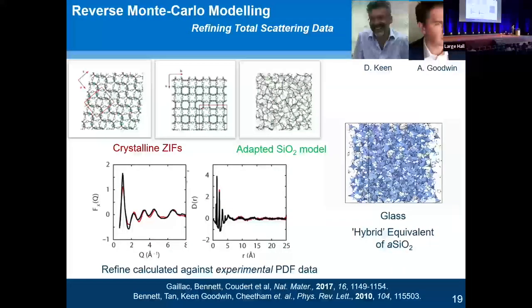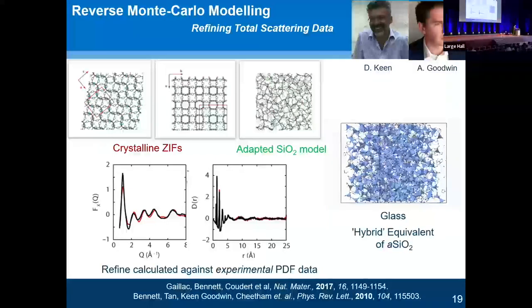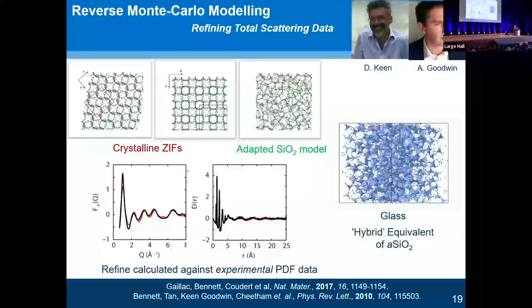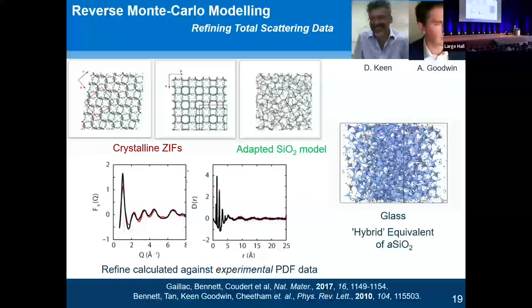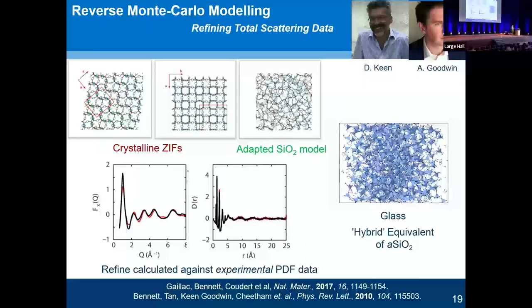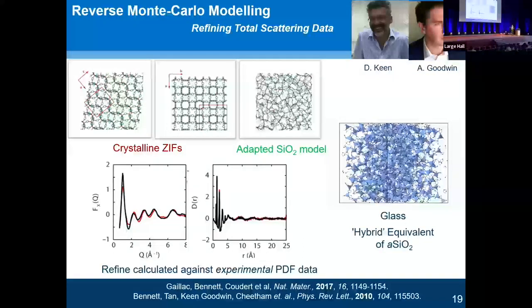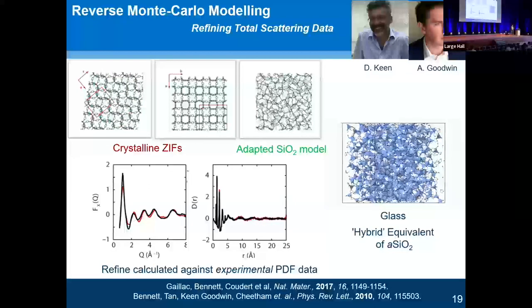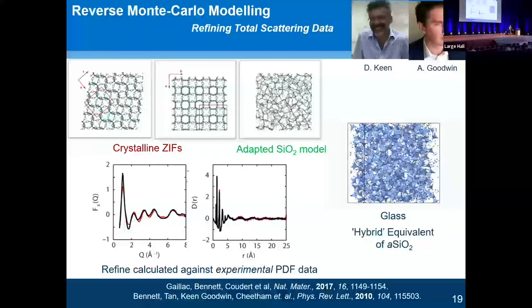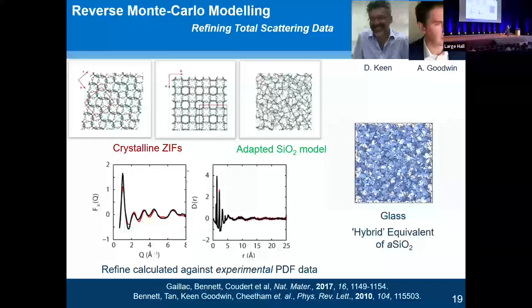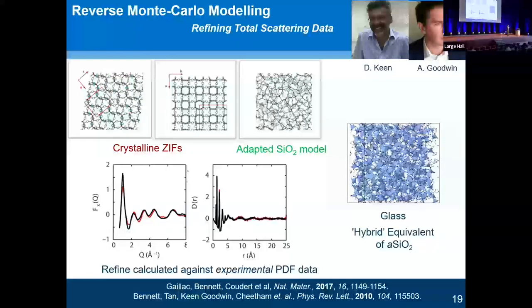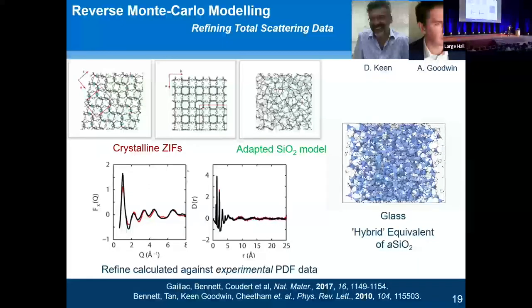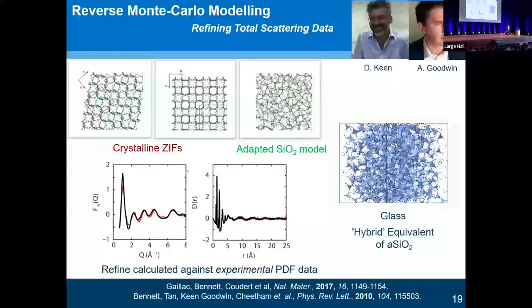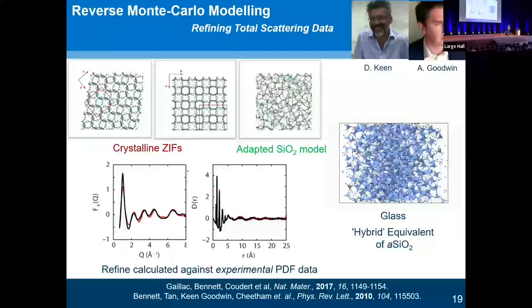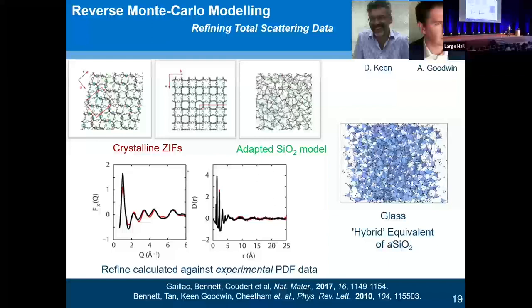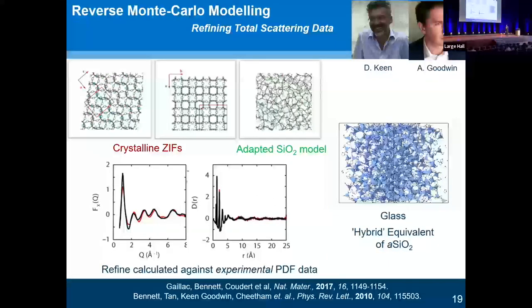I'm showing you many atomistic configurations, but I haven't told you how we produce them. Most of them are through reverse Monte Carlo modeling of PDF data, done with Andrew Goodwin and David Keen. Essentially, you collect PDF data, guess at a starting model, and move one atom from that starting model. You compare your new data to your experimental data, and if the agreement is better, you accept. If it's worse, you reject.